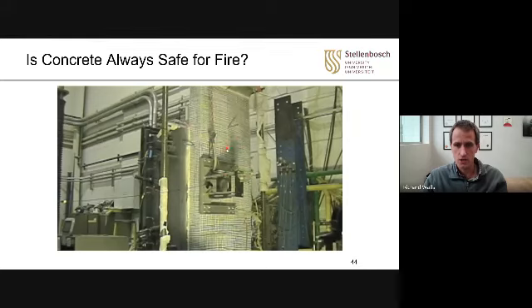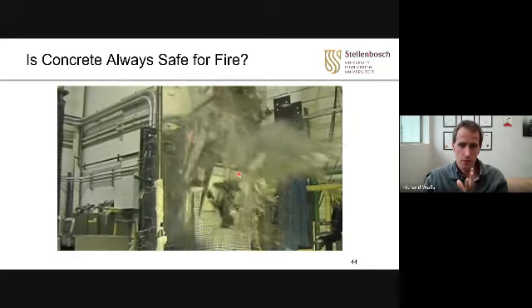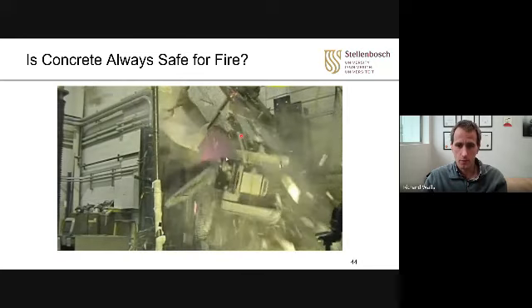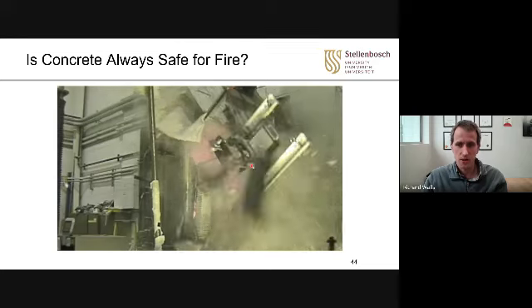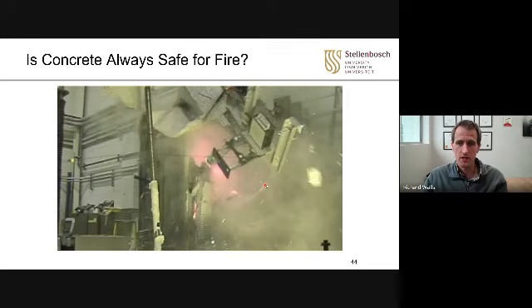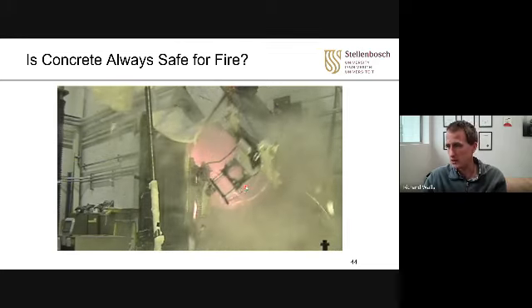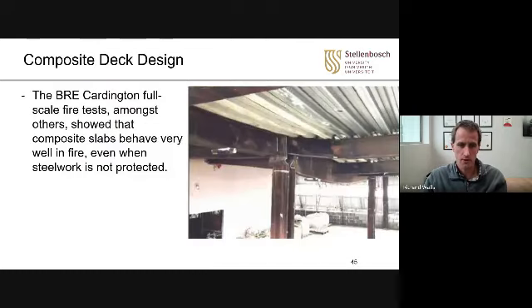So there you go. Just to show you once again. Bang. Heat it up until the point where it actually blew. Quite scary failure. Very, very problematic. That would cause a lot of damage to areas around.